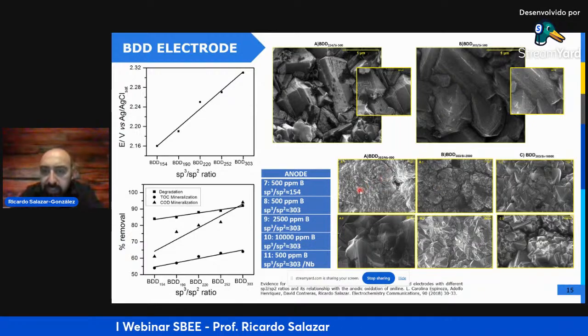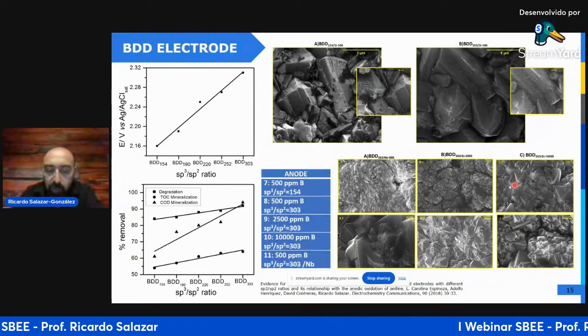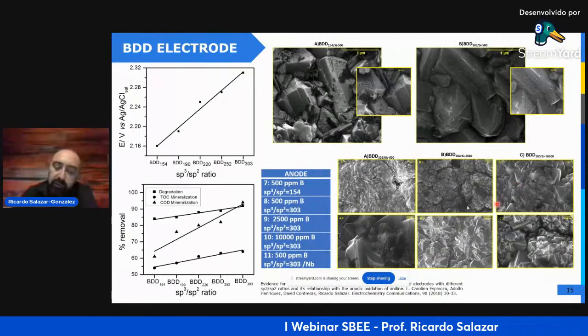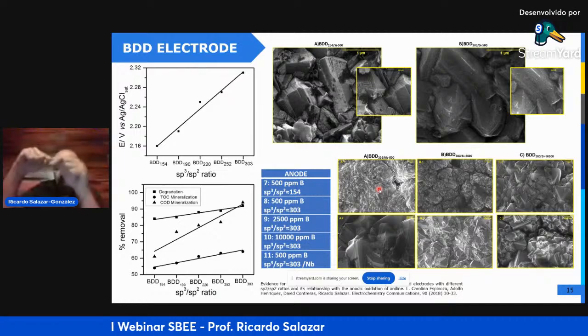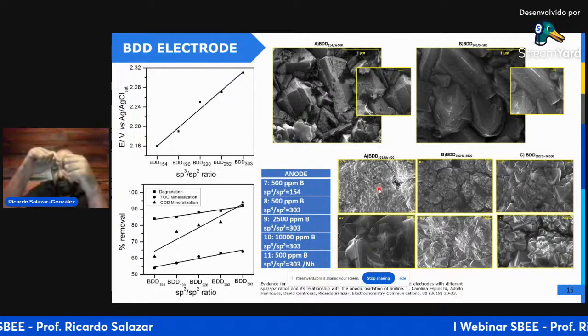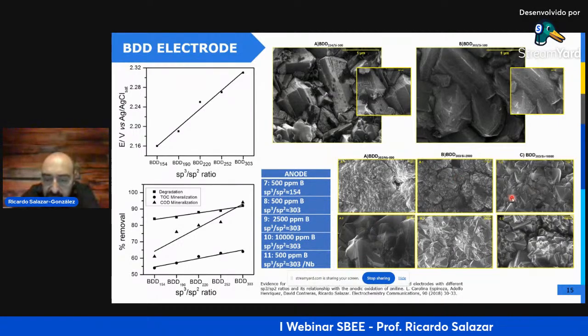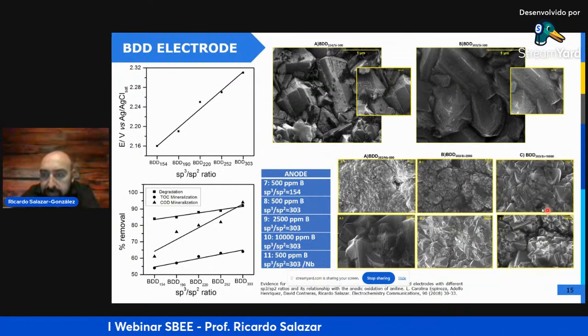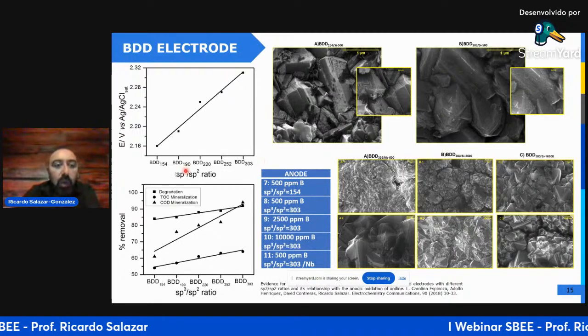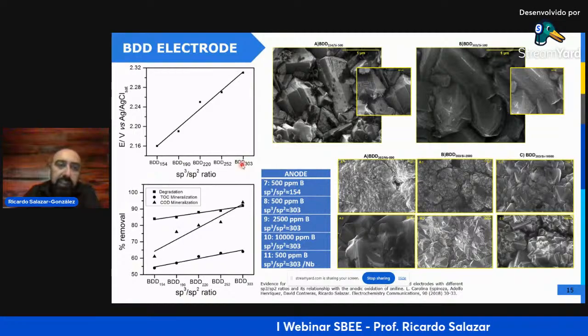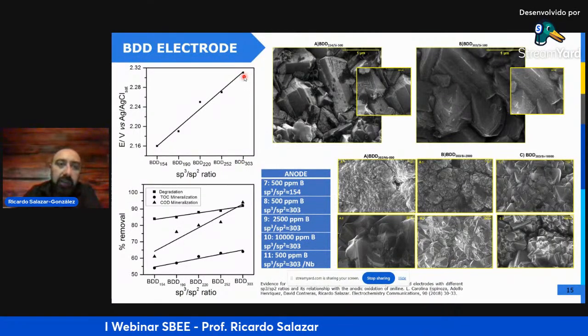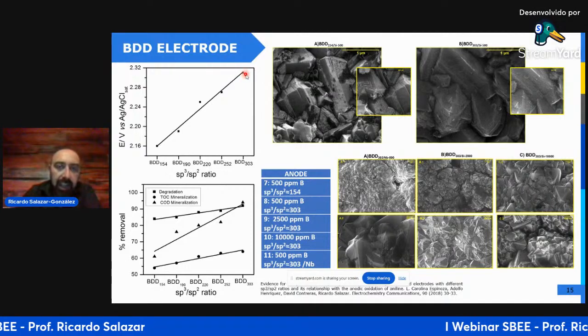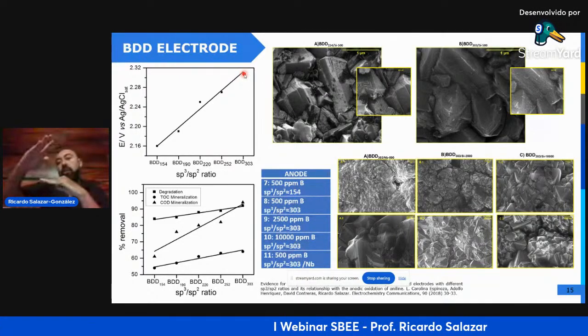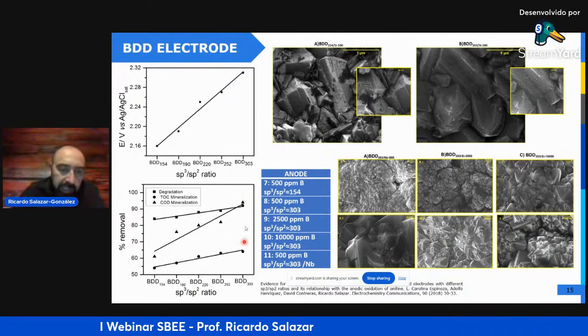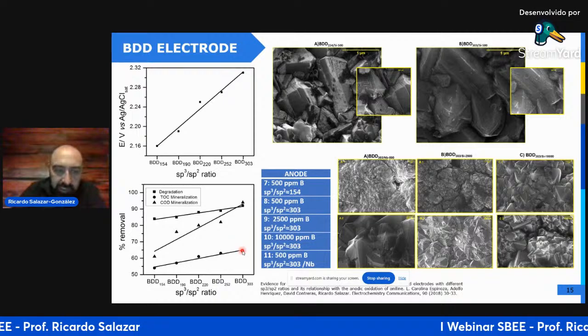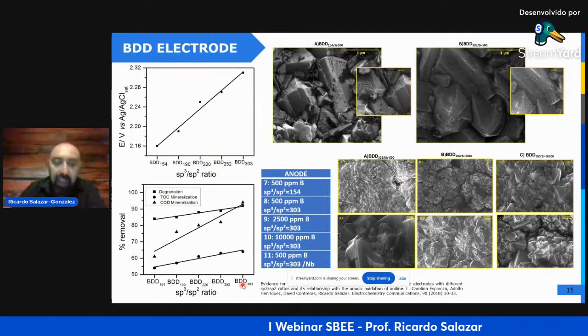But if we increase the boron doping, changes in the morphology are observed because the boron is introduced into the polycrystalline phase, causing a more amorphous surface. This morphology is known as rod-like morphology. And when we increase the content of diamond on the surface, we obtain a higher overpotential for the oxygen evolution. This is related to the higher concentration of hydroxyl radical, and for this reason, we obtained higher degradation of the pollutant when the diamond is in higher concentration on the surface.